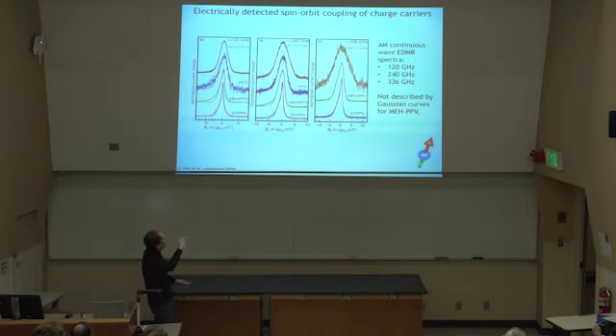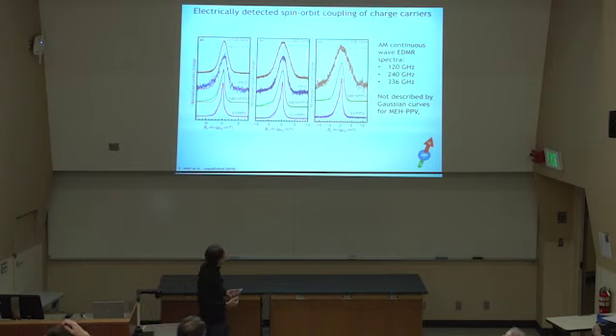You do it. What else did we do? Oh, proprietary polymers. We use commercial polymers that companies actually developed and built devices out of. And if you do all this, then you see that in this high magnetic field domain, 12 Tesla, where spin-orbit coupling governs these lines, you see all of a sudden